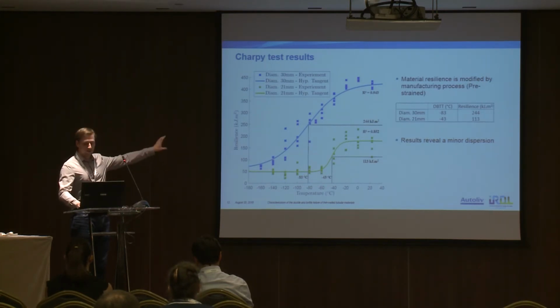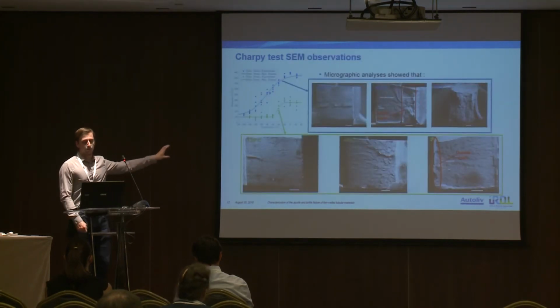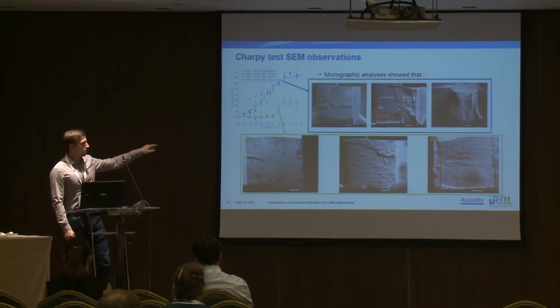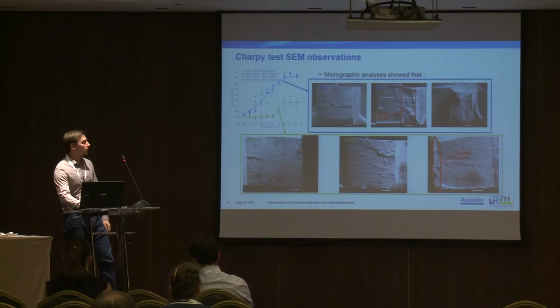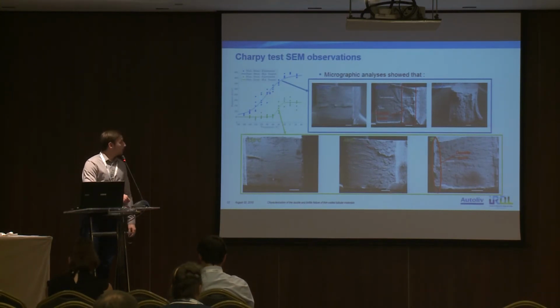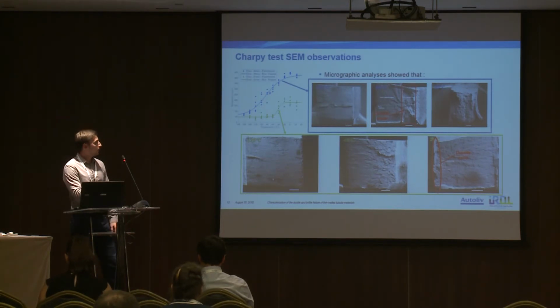And in order to explain this gap, we studied the fracture surface using SEM observation. Here you have the observations of the 30 millimeter diameter, and as you can see, at room temperature there is purely ductile failure behavior, while for the smaller diameter, 21 millimeters, there is only this part of ductile failure, and the rest is purely brittle failure.